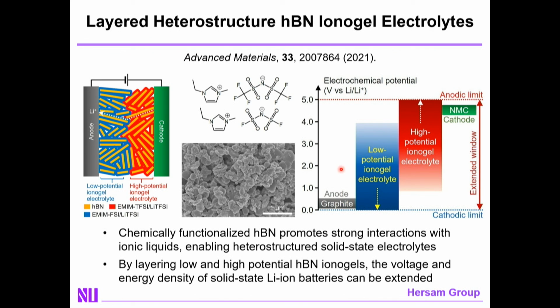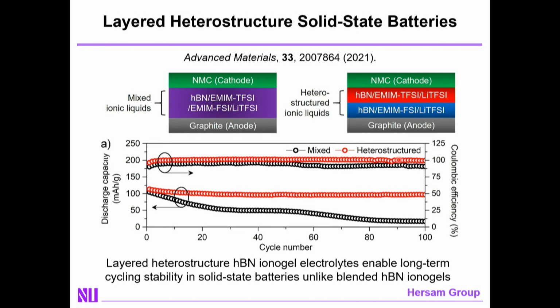The difference, though, with an HBN ionogel compared to an ionic liquid alone is that it's a solid. And as a result, we can now make a layered heterostructure where I put the high potential ionogel on the cathode side, the low potential ionogel on the anode side, and in that way we can achieve the full stability window from 0 to 5 volts. This indeed works quite nicely.